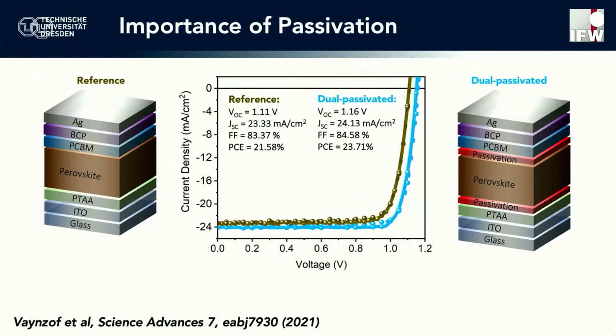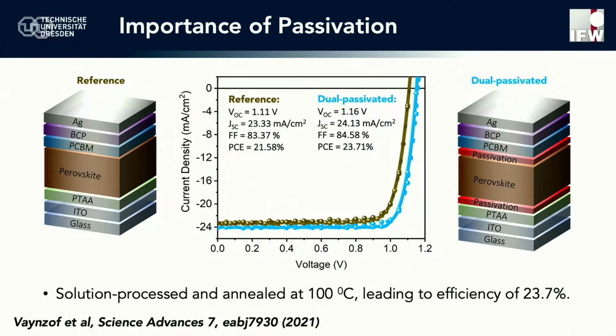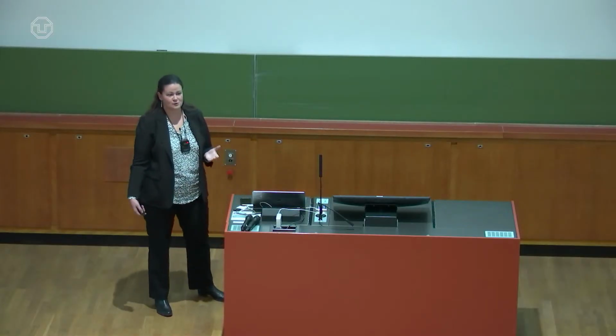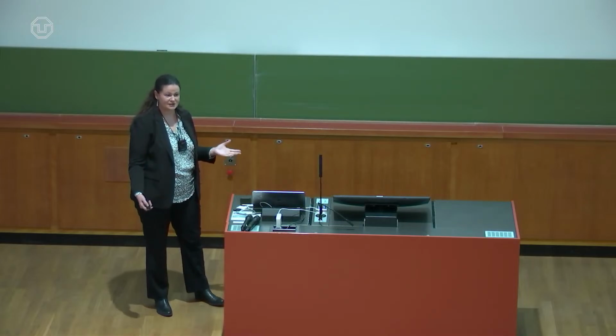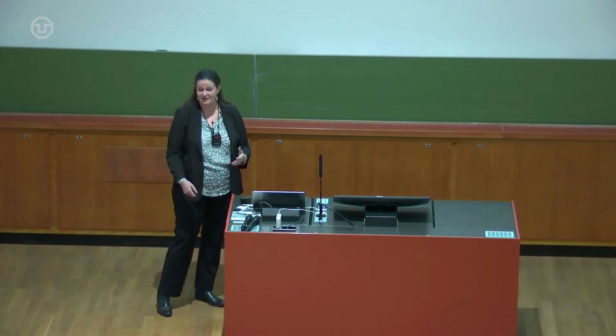Now, once we did that with this dual passivation strategy, both at the bottom and at the top, we were able to improve all the photovoltaic performance parameters, reaching an efficiency of 23.7 for a device that is entirely solution processed and at low temperatures of only 100 degrees. Now, while working with solvents is remarkable and interesting, it also opens opportunities for things like printing.